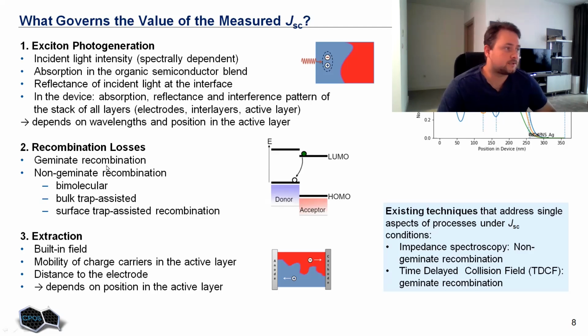First of all, I mentioned this splitting of excitons. So far we were talking about excitons, not free charge carriers. In order to contribute to external current, this exciton should be split into free electrons and holes at the interface between donor and acceptor material. That is possible only when excitons reach the interface before they annihilate. Moreover, they can also reach the so-called charge transfer state and recombine at the interface. That is a very short time scale process, up to 1 nanosecond, maybe a few nanoseconds, and that recombination is defined by geminate recombination. Also, there is non-geminate recombination.